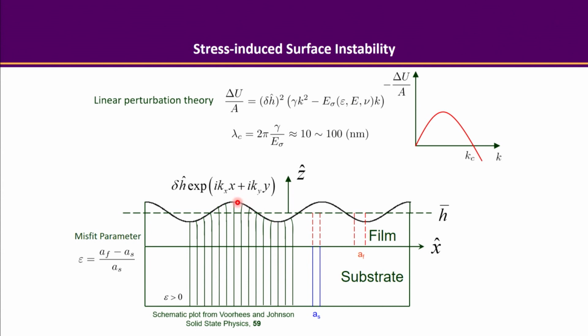So once the amplitude is amplified, that advantage of moving the atoms from trough to peak is going to be enhanced. So you are getting larger and larger energy difference. That's what we call instability. All right, so that's a very intuitive picture to explain how the ATG occurs.